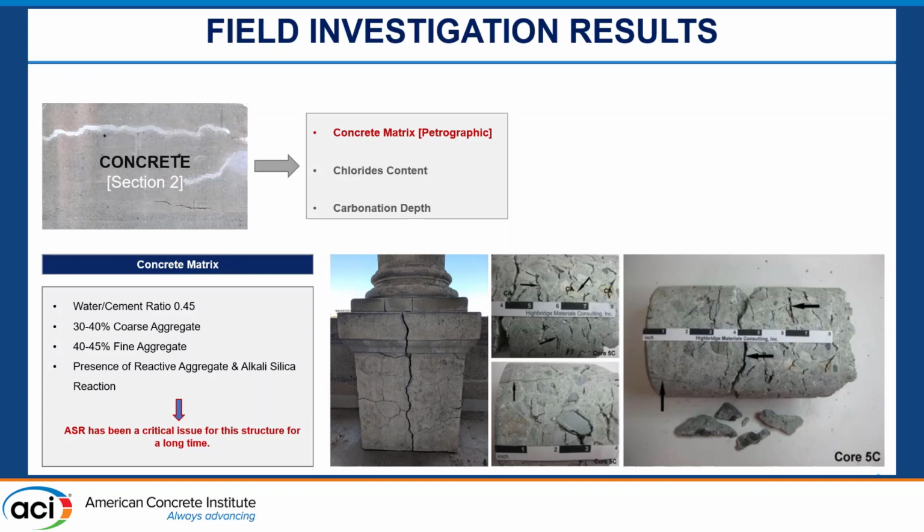When we looked at the mix design, nothing jumped out at us other than obviously there was a reactive aggregate, which we could see as an internal problem. So we wanted a technique where we could look at the onset of cracks, both on the surface and internal, and then look at how moisture was playing a role in the whole ASR process.